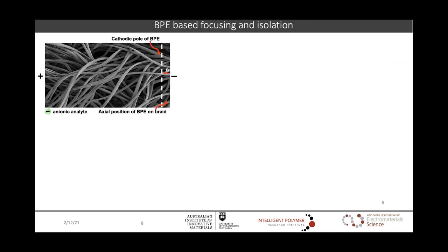Actually, there are two kinds of forces that act on the charged analyte in an electrofluidic system: the electroosmotic flow and electromigration. At position A, in the case of a negatively charged ion, the electroosmotic flow is greater than the electromigration, which drags the anionic solute towards the cathodic reservoir.